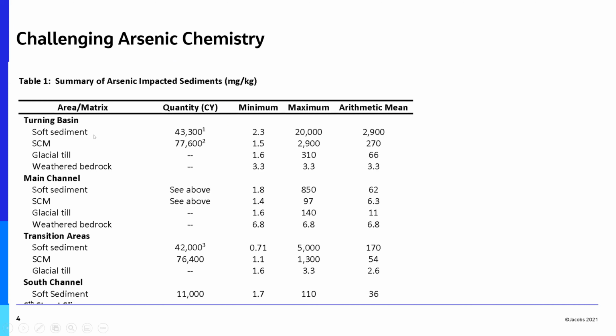So we had two main sediments that we were dealing with. We had a soft sediment which had a lot of organic matter in it, and what we called a semi-consolidated material. Both of these were sandy, silty materials, but the soft sediment had twice as much organic material in it, and as a result, it was very concentrated in arsenic. So you can see the quantities to be removed based on the bathymetry, where the soft sediment in the turning basin was about 43,000 cubic yards. In the transition area, it was about the same. I hope you can see my cursor here, 42,000.